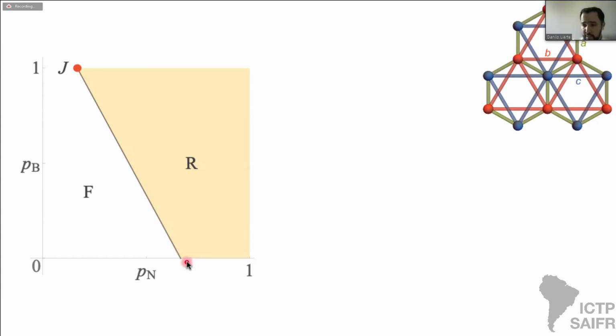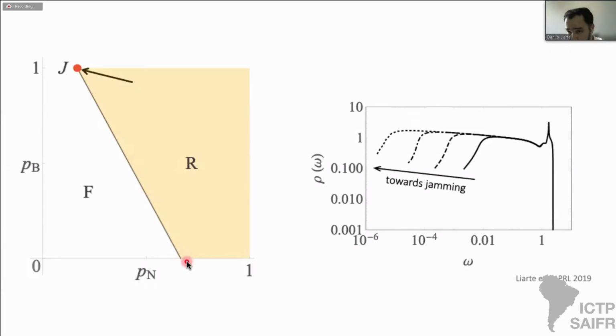I have already described the static elastic behavior, so you might be interested in knowing what other properties these rigidity transitions have. For instance, can we find a boson peak as we approach the J point over there? And the answer is yes, we can. And just as a reminder, the boson peak is a typical anomaly that's popular in the glass community, where it's often described as a rounded maximum in plots of the structure function. It's also connected to an enhanced population of low energy modes that leads to a flat density of states at low frequency. And so here what I'm showing is our calculation for the density of states for points approaching the jamming point from the solid to the dotted line. And the behavior is just as expected.